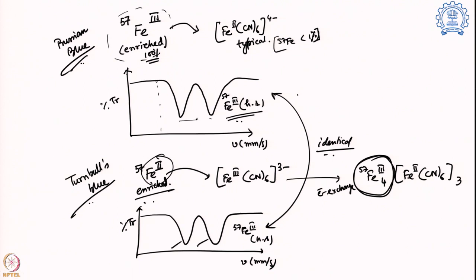So that is why this signature is exactly the same as Prussian blue. If it were an iron 2 which is not reacting with the sample, then I would have gotten a different signature, comparable to an iron 2 high spin system, but over here I am getting an iron 3 high spin system, which again proves the concept that yes, the reaction is exchanging an electron in between. So Mössbauer spectroscopy again came to the rescue to find out what is actually happening in the reaction media. And this particular reaction was done by Meyer and co-workers, who rationally used iron 57 in this sample and figured out that I am going to get a similar kind of result which showcases the electron exchange in between.